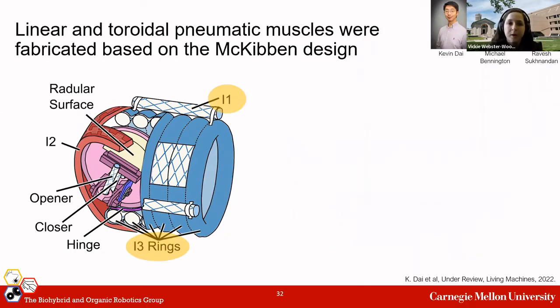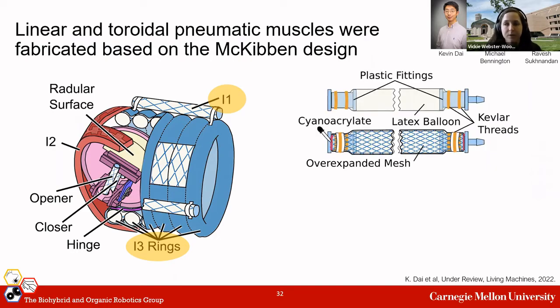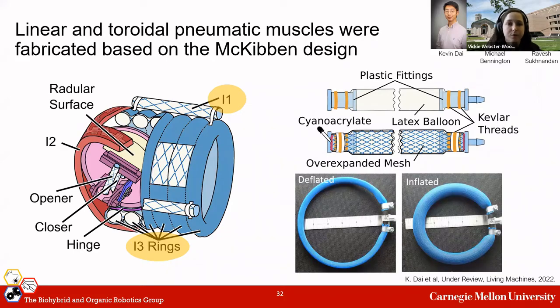Okay, so for the robot, for the primary retractor muscle, I3, and the external I1 muscle, we use McKibben-style pneumatic artificial muscles. In order to achieve the larger contraction ratios that we needed to mimic aplysia muscle, these actuators are fabricated with a latex balloon as the internal bladder, housed within an overexpanded mesh. And then as the balloon inflates, the overexpanded mesh restricts its motion so that we get contraction along the axis of the actuator. The I1 muscle is relatively straight in the animal, so we use the standard linear McKibben design. And for the I3 muscle, we approximated this as a series of toroidal rings.